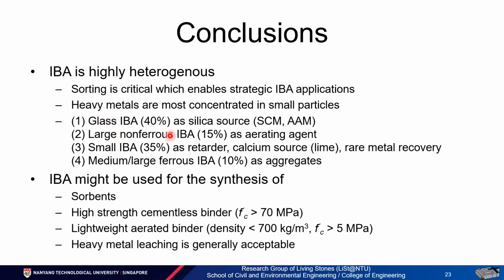The glass IBA is around 40%, and these IBA particles can be used to provide silica-rich sources. The large non-ferrous IBA, which is about 15%, has good potential for aeration. Whereas the 35% of smaller IBA particles can be considered as a retarder, as a calcium source, and can be used for rare metal recovery. The remaining 10% of medium to large ferrous particles will be a good source for aggregates.